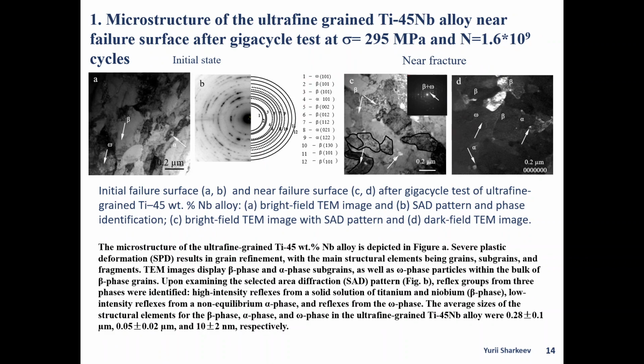The microstructure of the ultrafine grain titanium niobium alloy is depicted in Figure A. Severe plastic deformation results in grain refinement, with the main structural elements being grains, subgrains, and fragments. TEM images display beta phase and alpha phase subgrains, as well as omega phase particles within the bulk of beta phase grains. Upon examining the selected area diffraction pattern, reflex groups from 3 phases were identified.